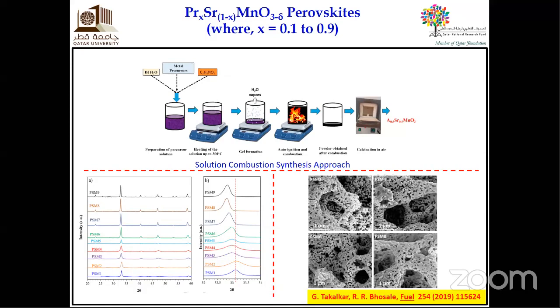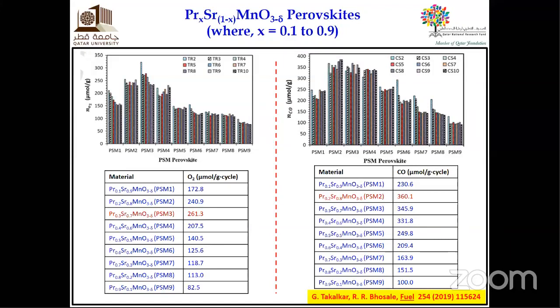So we developed around 9 PSM perovskites to find out which one is the best, because in the previous study we found that Pr0.5Sr0.5 was the best, but we don't know if 0.1 and 0.8 have a different role to play. When we compare, you can see that in terms of thermal reduction capacity, Pr0.3Sr0.7 is more beneficial, because if you check the numbers, it produced the highest amount of O2. This material can produce the highest amount of O2. In terms of CO production capacity, Pr0.2Sr0.8 is the most efficient. Even Pr0.3Sr0.7 is almost number 2 in this case.